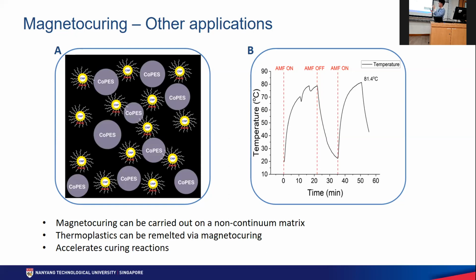Between AMF on and AMF off, the temperature profile is almost identical. And what this means is that magneto curing can be used for recycling of thermoplastic. In addition, magneto curing can be used to not only initiate curing processes, it can also accelerate curing processes because it is supplying heat, and with the heat that's supplied, the rate of reaction will increase exponentially.